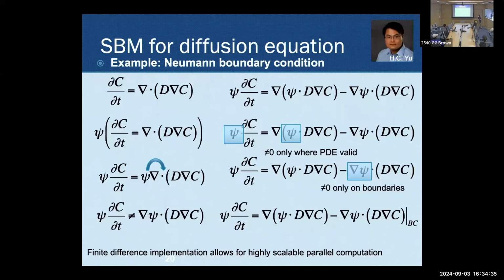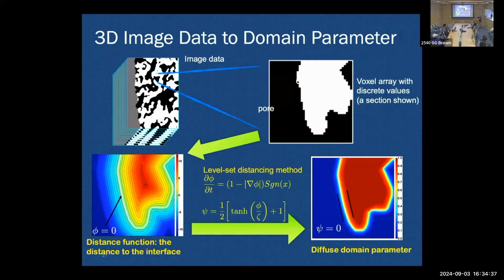The nice thing about this diffuse interface approach is that I can start from an image, a segmented image. You have something like this, if you zoom in. Then I evolve this level set distancing equation. You just evolve it, and what you get is something called a level set. At the boundary, this phi is going to be 0.